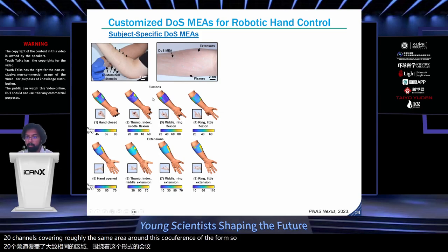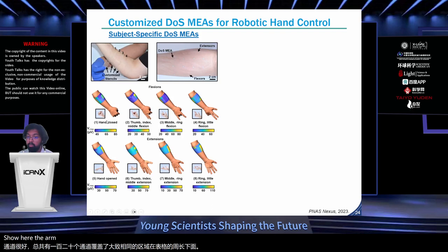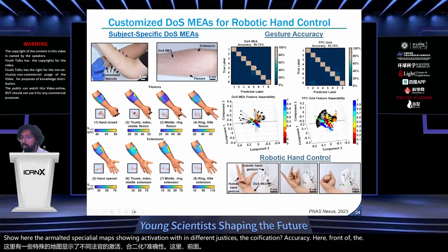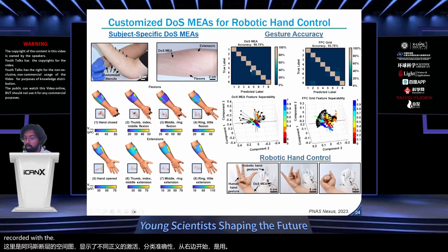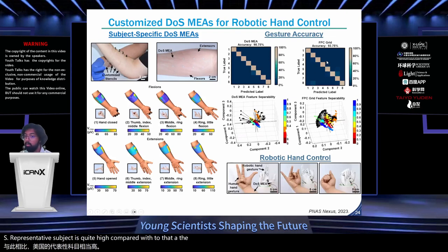So below, we show here the RMS voltage spatial maps showing activation for the different gestures. Classification accuracy here, shown on the right, for the EMG recorded with the DOS MEA for this representative subject is quite high compared to that of the FPC. And the feature separability from principal component analysis also explains why this data from the DOS MEA is far more distinguishable. So less redundant, and the subject was able to control a robotic hand in real time.